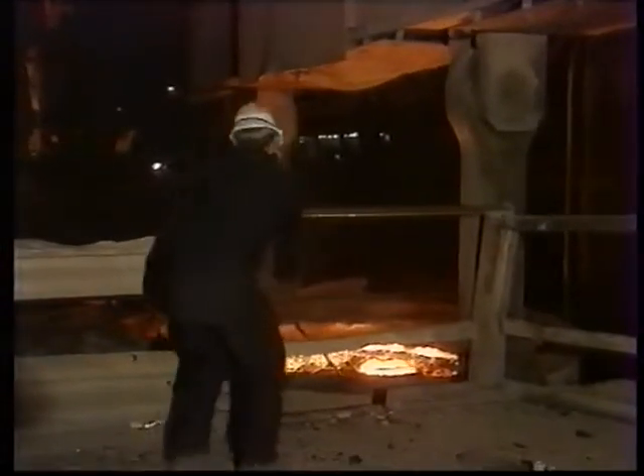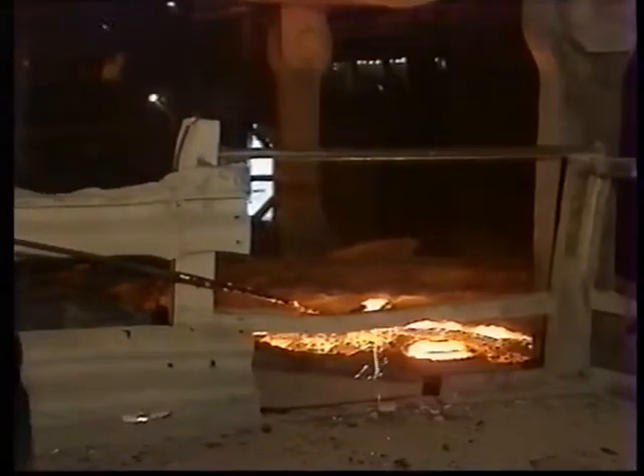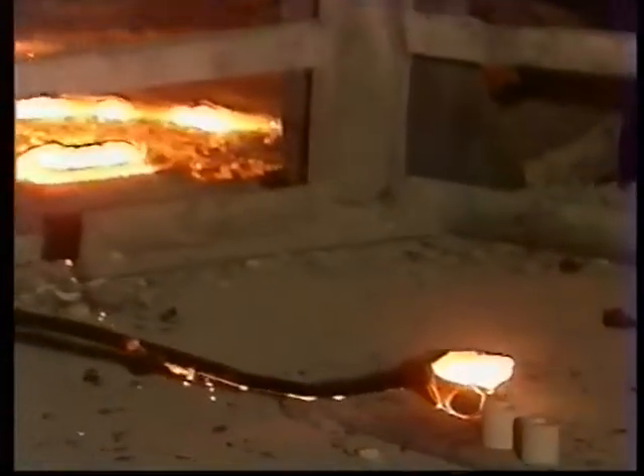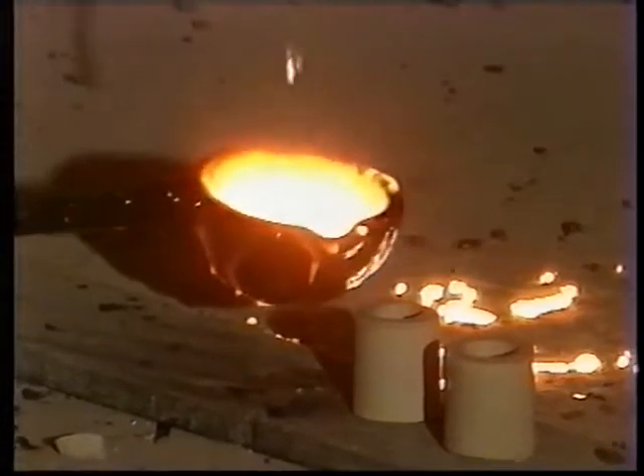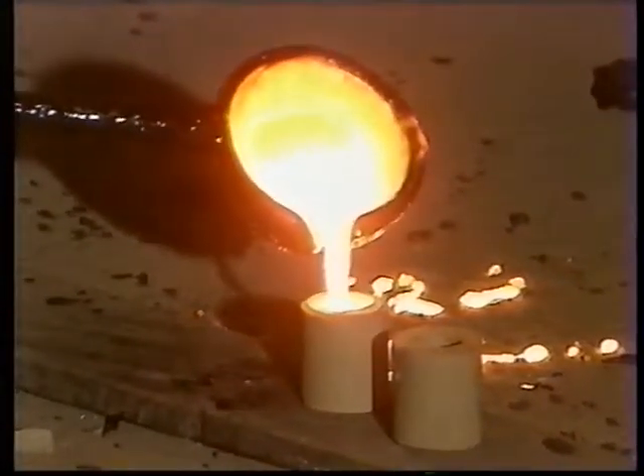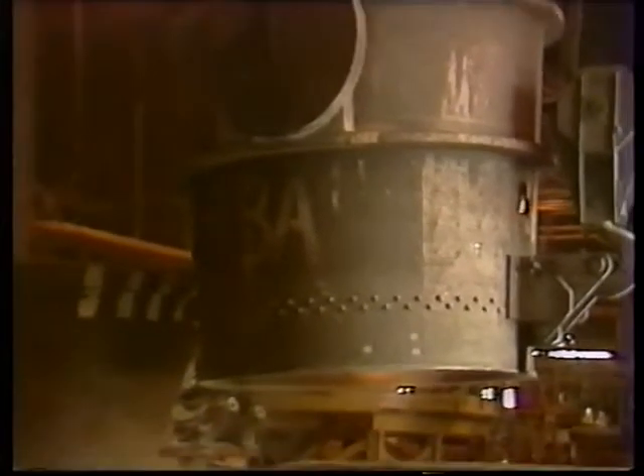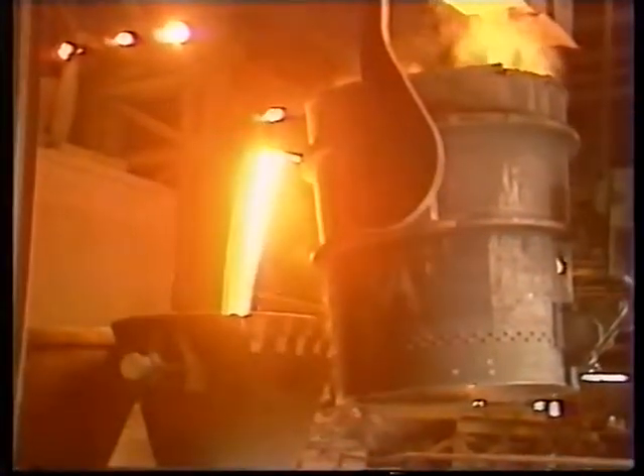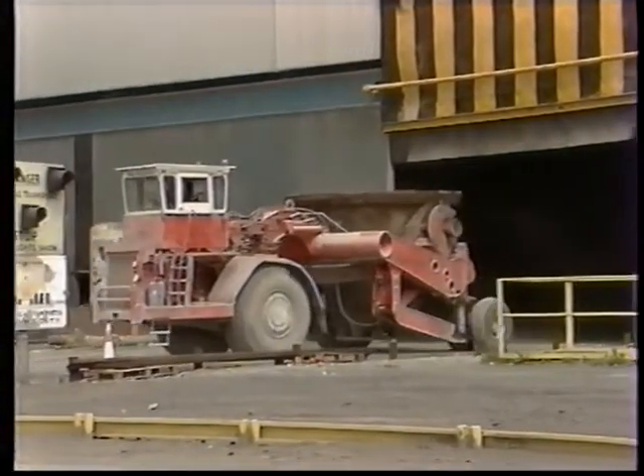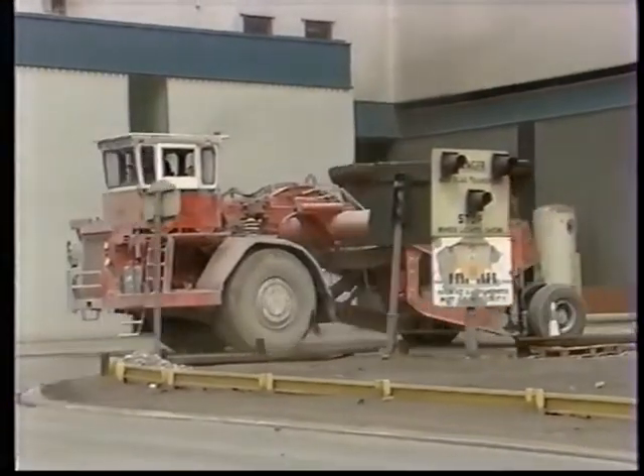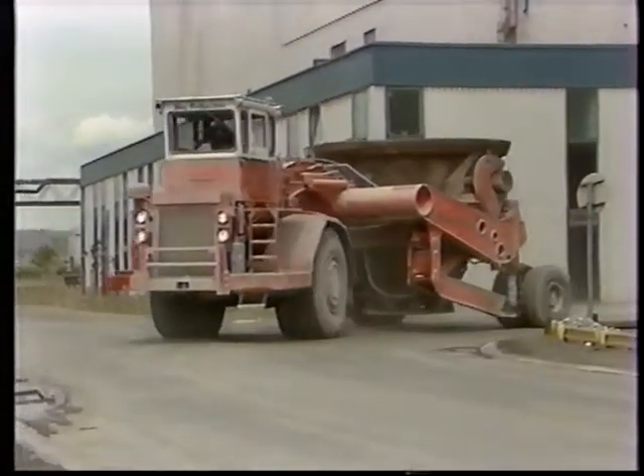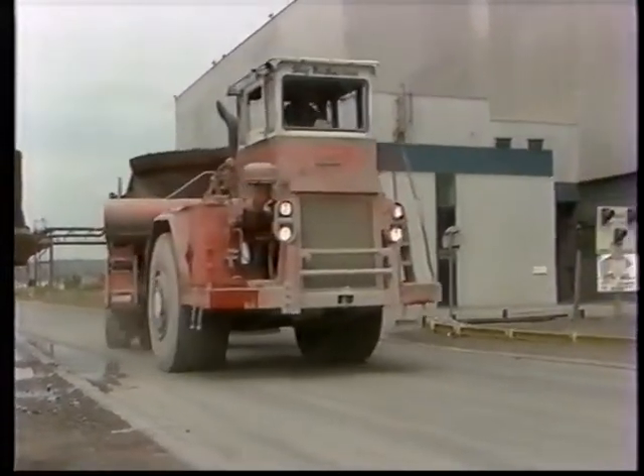Because of the inherent dangers present whenever liquid steel is handled, no one is allowed to work in the melting shop without full safety equipment: fireproof trousers and jacket, safety helmet and molten metal visor, and of course foundrymen's boots. Having absorbed the melt impurities, the molten furnace slag is poured off to ensure that only metal is transferred to the AOD vessel, and then the charge is weighed. Slag is removed from the bay by a specialist slag transporter. The metal content is recovered for reuse while the residual slag is turned into roadstone.